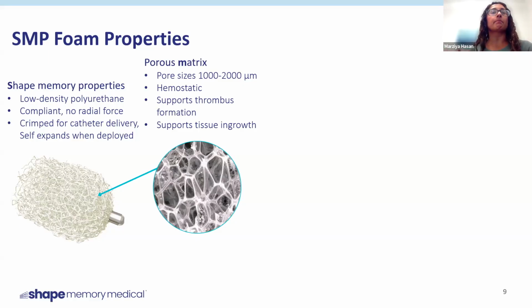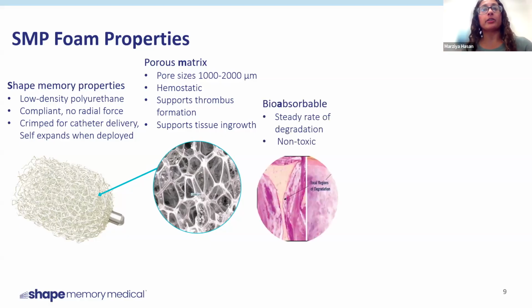Because of these porous materials, as the blood is getting pooled into the various foam cells, there's clot being formed, and eventually that results in stable tissue ingrowth. Another thing is that our material is bioabsorbable. That just means that it'll degrade over time, and we have done some work to show that the byproducts from this degradation are non-toxic.